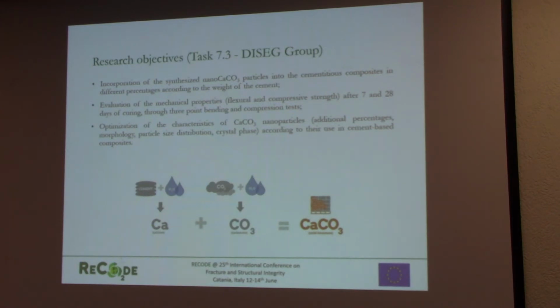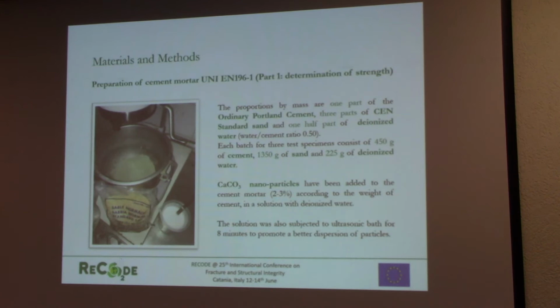obtained via precipitation of CO2, the evaluation of the mechanical properties in terms of flexural and compressive strength, and of course the optimization of the characteristics of calcium carbonate nanoparticles according to their use in cement-based composites. Probably I can skip the preparation of the cement mortars. We use the standard procedure that is regulated by the regulation of the European Union.